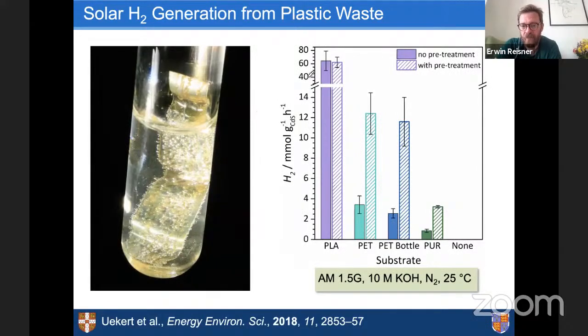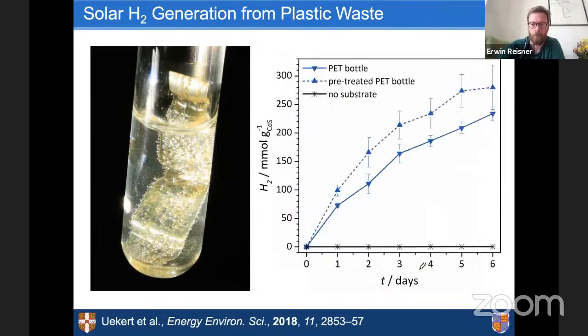So here you can see a little bit the type of plastics we can convert. Polylactic acid, also discussed in the previous lecture, PET, polyethylene terephthalate is good, a real bottle or just pure PET. Polyurethane is a possibility, a bit less efficient. And that's more or less at the moment the plastic we're looking at. So this really means condensation polymers. And the stability, same for the biomass, it's quite stable. So usually we run these experiments for about a week and stop afterwards, but the systems are still active afterwards.